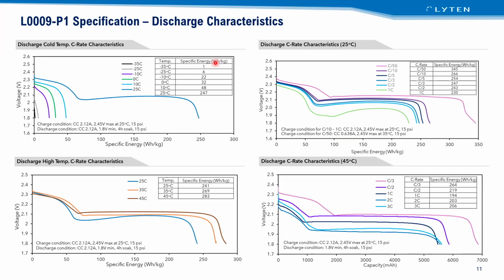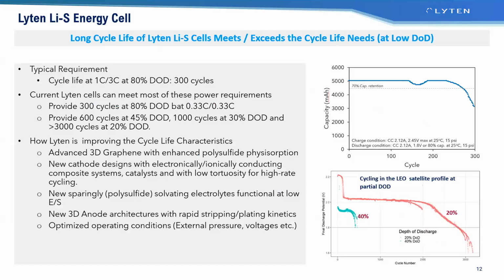So that plot over there on the left, that's the reason why Tesla is warming up batteries before charging. Yes, it is. Because what happens with a battery is it's all diffusion. You've got an electrolyte, you've got a salt moving through an electrolyte. When you drop the temperature, it all slows down, right? And this cell is pretty good down to lower temperatures. The first plateau, you get that capacity out, but you start losing that second plateau because that chemistry slows down a lot when you get really cold. But when you leave the car at Tahoe outside, you have a limit. You do. You have to do something. That's going to be true of any chemistry, because it's all diffusion and chemistry. We all know chemistry slows down at lower temperatures.